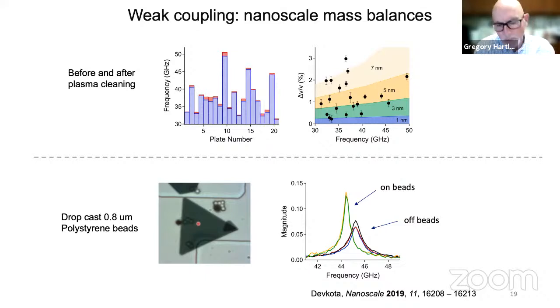I think this is a little surprising to me because, basically, the vibrational mode, the breathing mode, is a normal mode of the plate, right? So it has amplitude all over the plate, but we're seeing different frequencies in different spatial regions. So there must be some hybridization that's going on caused by the beads that causes a localized mode here and modes that are different in different regions of the plate. So this is actually, I think, more complicated than what this experiment might look like.